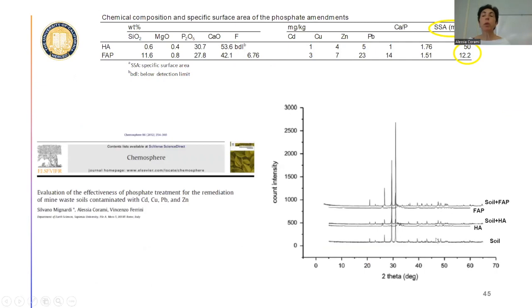The other point is that we plotted again our solid samples after characterizing them with the XRD. So you can see the XRD from the hydroxyapatite and the fluorapatite from US, and they show the same behavior as the supernatant. And then in California, I analyzed the specific surface of the 2 phosphates, in particular the hydroxyapatite, which has a really high value, and the fluorapatite from US shows a low value. And this can explain why the fluorapatite from US can absorb a lower amount of metals compared to the Moroccan fluorapatite, because of the specific surface area.